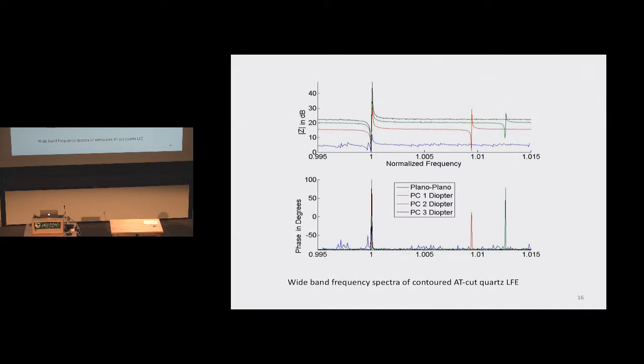This is the normalized frequency, which is the frequency of the device divided by the transverse shear mode resonant frequency, and you get a very clean spectrum over here. Similarly, over here on the phase, you got rid of these two, and you ended up getting a very clean spike, again, at the appropriate point. So basically what we found is, yes, you can excite that transverse shear mode. You must be careful in terms of the orientation of the electrodes, that the actual electric field is perpendicular to the electrode spacing, and finally, make sure that it is planar convex.